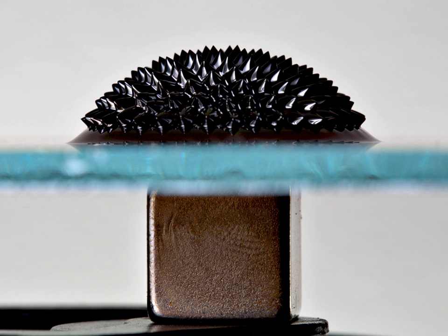Samarium-cobalt magnets, chemical formula SmCo5, the first family of rare earth magnets invented, are less used than neodymium magnets because of their higher cost and lower magnetic field strength. However, samarium-cobalt has a higher Curie temperature, creating a niche for these magnets in applications where high field strength is needed at high operating temperatures. They are highly resistant to oxidation, but sintered samarium-cobalt magnets are brittle and prone to chipping and cracking and may fracture when subjected to thermal shock.